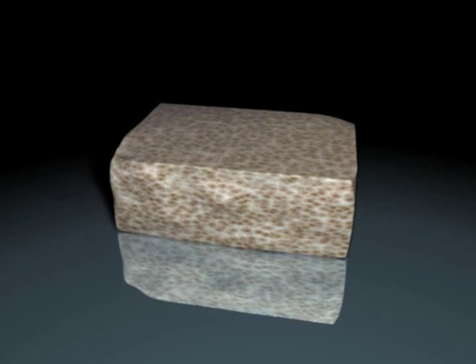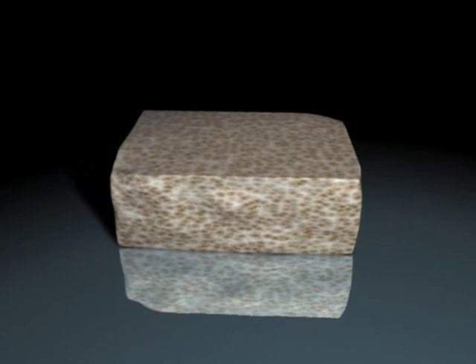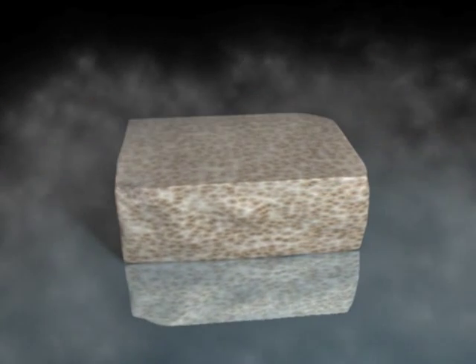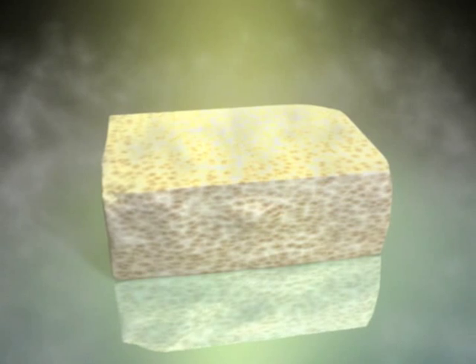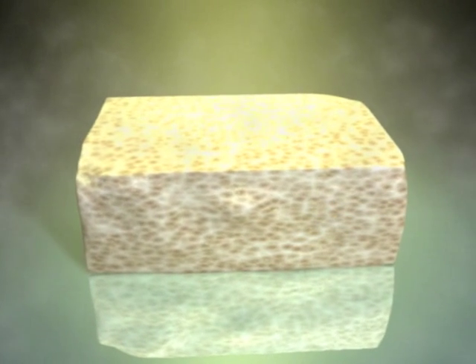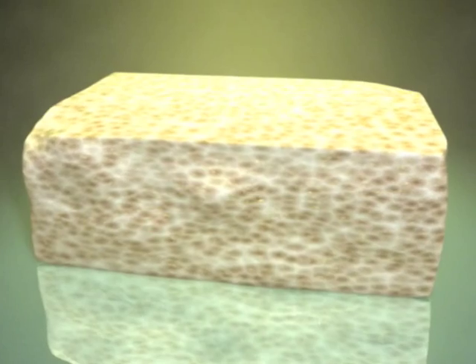The final step is sterilization with low-dose gamma irradiation at dry ice temperatures, which results in a sterility assurance level of 10 to the negative 6 while maintaining the biomechanical integrity of the tissue.